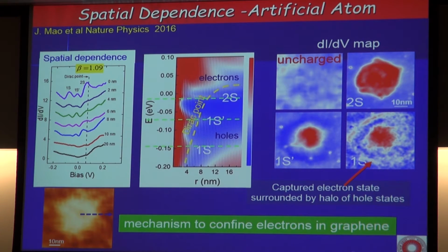So it's not individual electrons, right? It is not like I'm adding electrons. It's a charge, and it's a continuous thing, because it depends on your wave function. So it depends on where you look. In fact, the net charge over the whole sample is 0, but you have a concentration of positive charge here and Friedel oscillations that decay. So that's why I use beta rather than charge, and it's not a discrete charge. It is really a continuous charge.